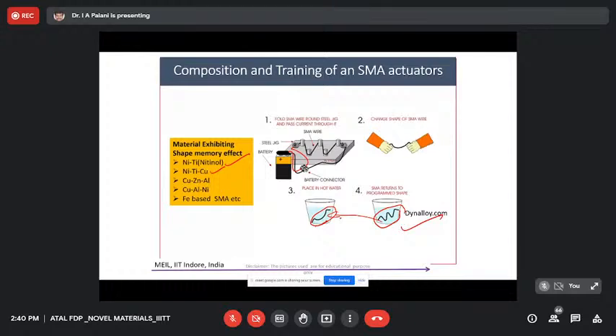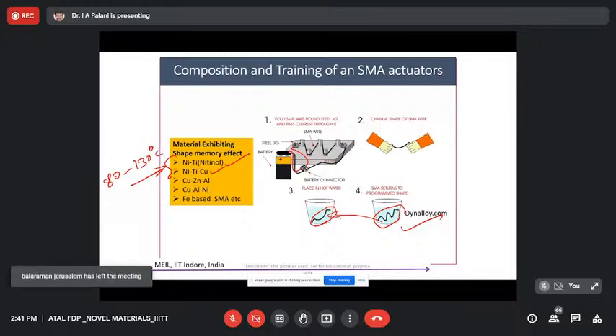But fundamentally, when do we need to go for nickel titanium and when do we need to go for copper-based shape memory alloys? In the case of nickel titanium, if my actuation temperature is within the range of 80 to 130 degrees Celsius, I go for nickel titanium based shape memory alloys. And if my actuation is in the range of 250 to 350 degrees Celsius, then I go for copper-based shape memory alloys.